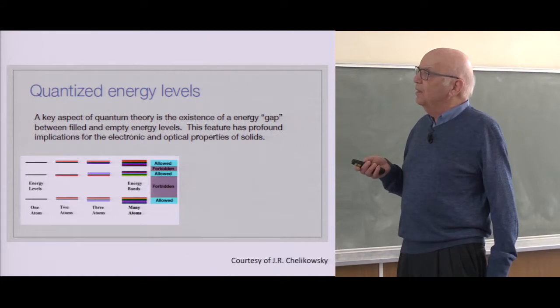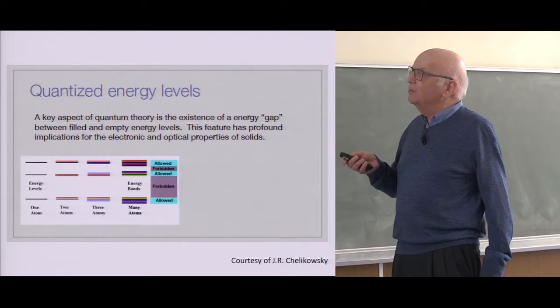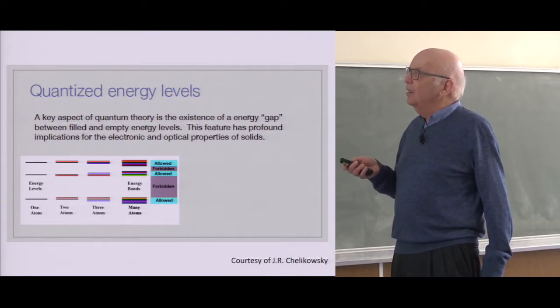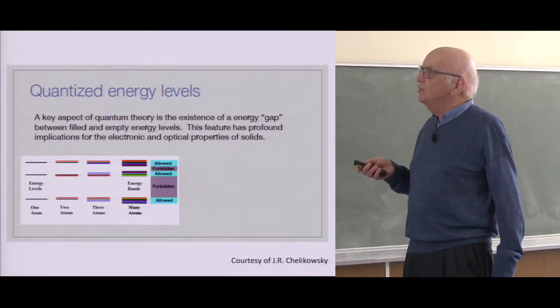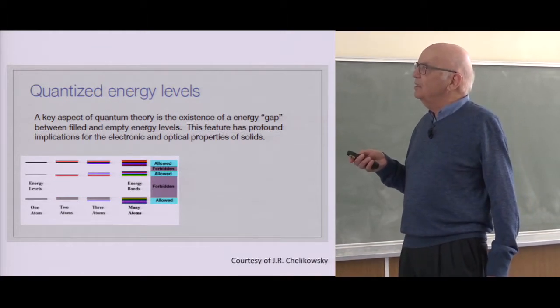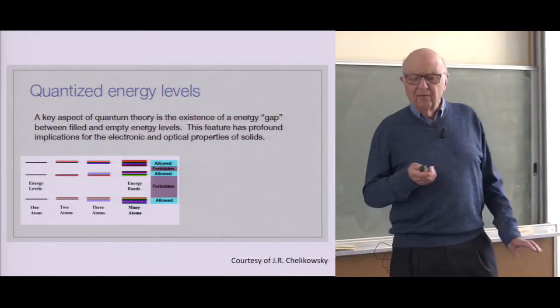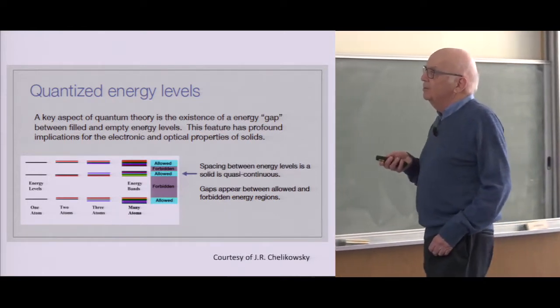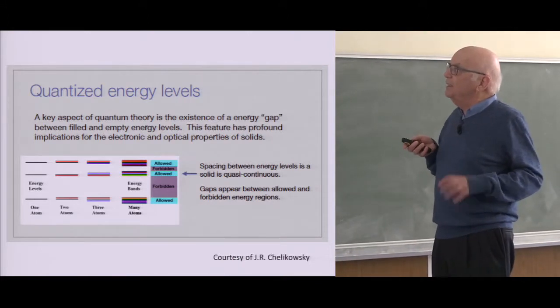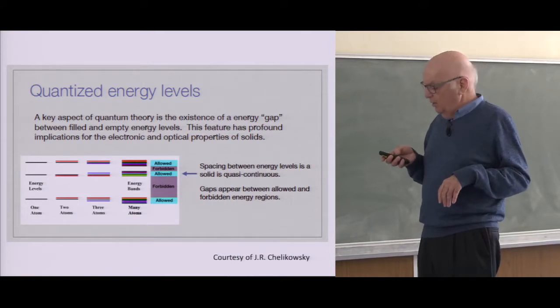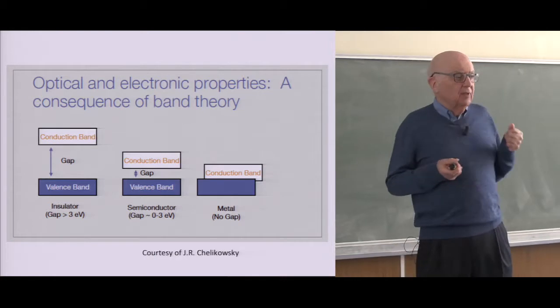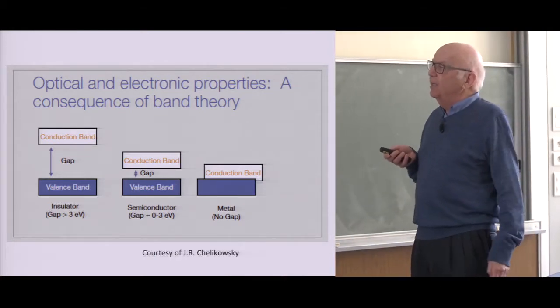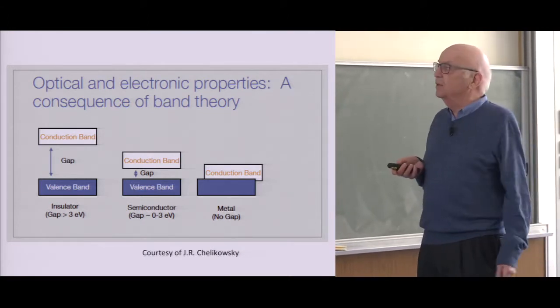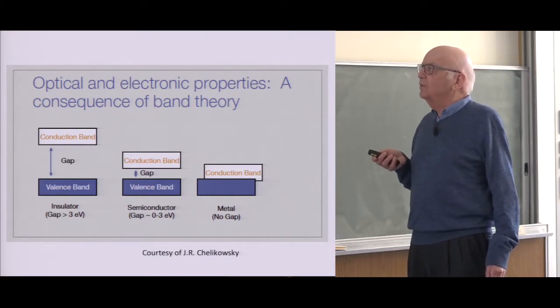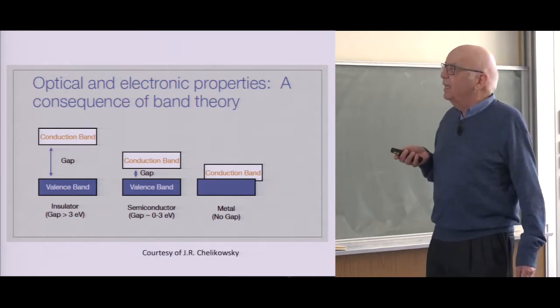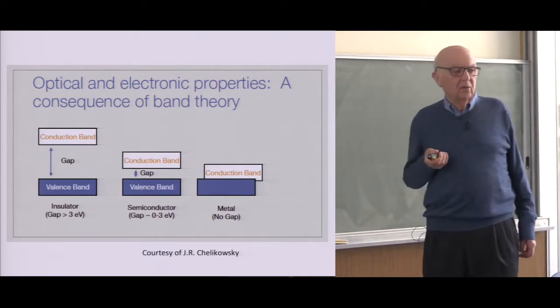Well, you know for an atom, there are discrete energy levels. And if you put two atoms together, you'll have two levels, then more for three atoms. And then for many atoms, you get this. And so when you get to the solid, you have these allowed states of energy levels and forbidden regions. And that forbidden region leads to the energy gap. So when atoms get close enough together, the spacing is so small that it's quasi-continuous, and you get the gaps. So the answer to the age-old resistivity problem is that if the gap is bigger than 3 eV, you get insulators. You get diamond, for example, quartz. If the gap gets small enough, and let's say without doping, you get semiconductors, where the conductivity is temperature dependent. And if there's no gap at all, then you get a metal or a semi-metal.